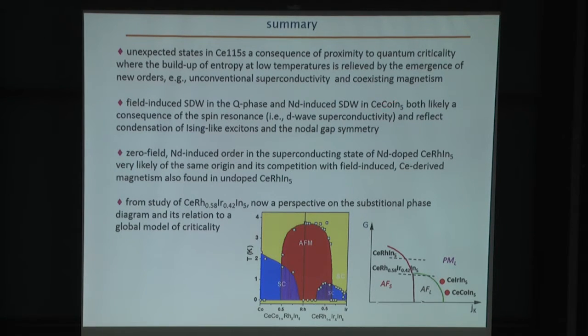So in cerium cobalt indium 5, we've seen that a magnetic field as well as neodymium substitution for cerium induces a spin density wave order inside its superconducting state. And it seems that both of these spin density waves are a consequence of the existence of a spin resonance, which is a result of d-wave superconductivity, and that these magnetic orders, these spin density waves, reflect simply the condensation of excitations in that spin resonance.